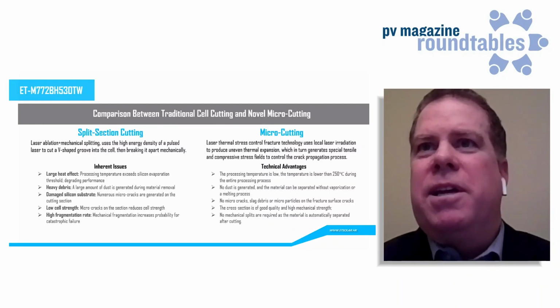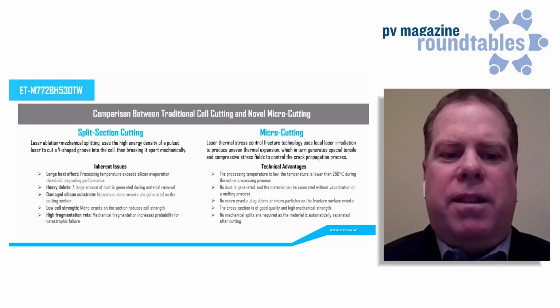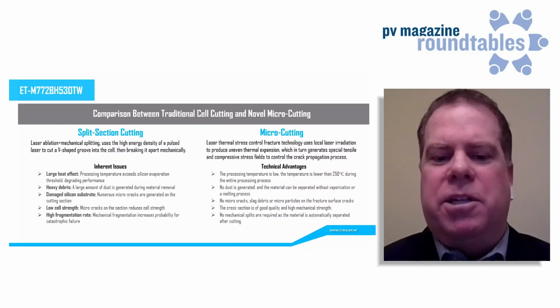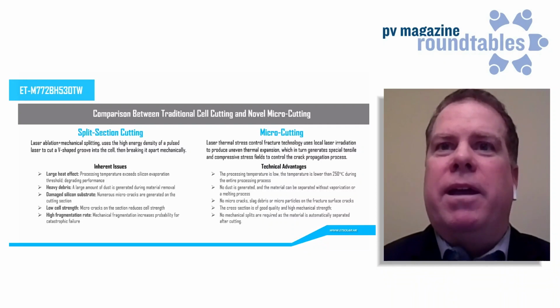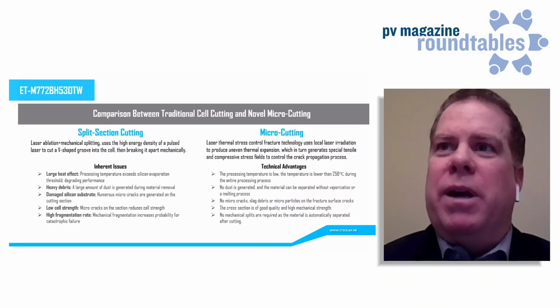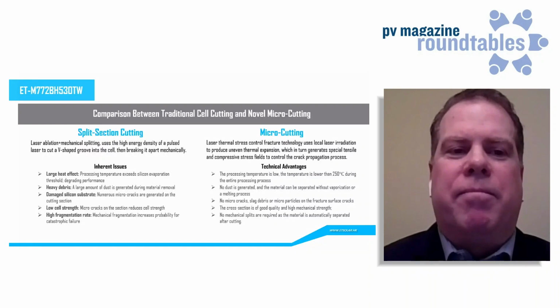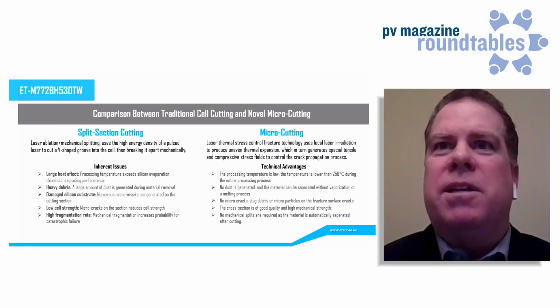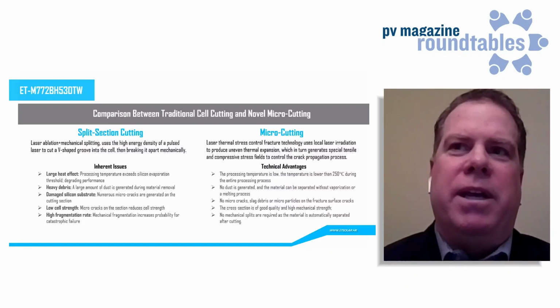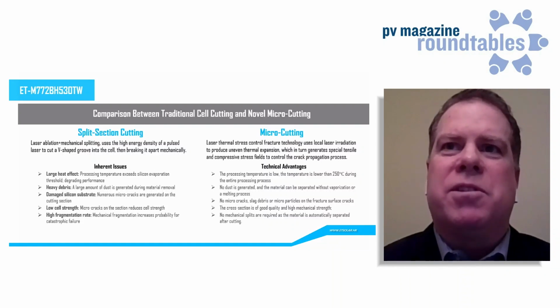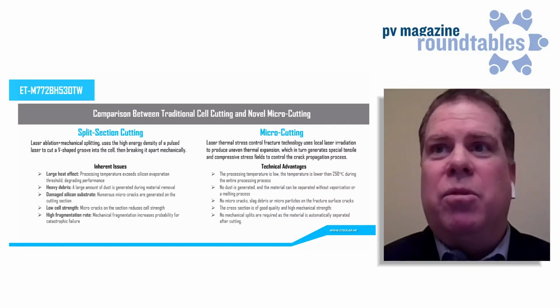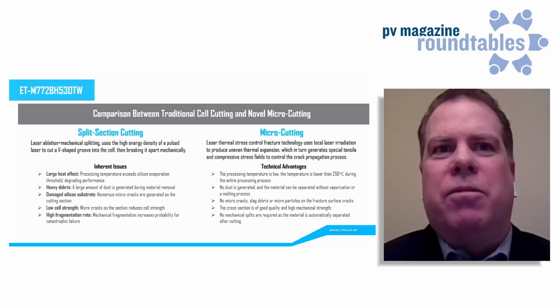So ET Solar has taken the microcutting approach, and this, I guess, begins with a partially prefabricated groove into the material, plus a new thermal stress controlled fracture technology. So through a low power laser, you can do a local irradiation to the area to be split. This creates an uneven thermal expansion within the material, which in turn generates some unique tensile and compressive stress fields, and these can be controlled to instigate a crack propagation process through the cell.